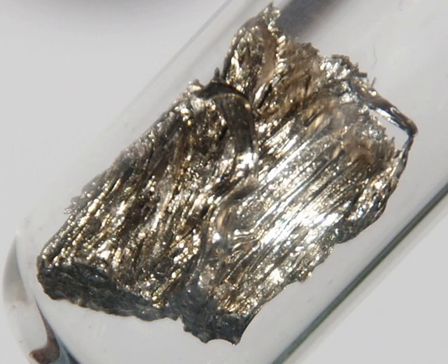The co-precipitation leads to nanocrystallites of the order of 100 to 200 nanometers in size, and their sensitivity as X-ray storage phosphors is increased an astounding 500,000 times because of the specific arrangements and density of defect centers in comparison with microcrystalline samples prepared by sintering at high temperature. The mechanism is based on the reduction of Sm3+ to Sm2+ by trapping electrons that are created upon exposure to ionizing radiation in the BaFCl host.